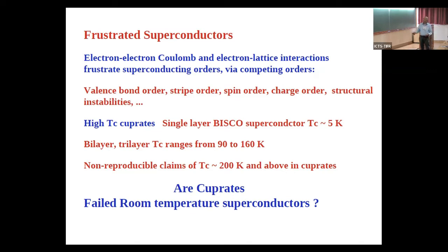If you take a single-layer cuprate superconductor, TC is 5 Kelvin. Create a bilayer with almost the same normal properties, and the TC goes up to 160 Kelvin. There have been non-reproducible claims of TC of even 200 Kelvin in earlier times. It doesn't mean that it doesn't exist. The cuprate seems to have its own mind. We'll see what it is. Some people claim that cuprates are failed room temperature superconductors, because if we take some of the theories seriously, the intrinsic TC can be as large as 300 Kelvin for the available parameters. But you never see anything above 150 or 160.